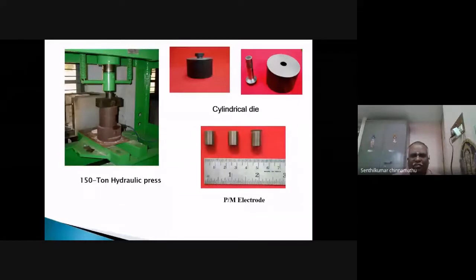And finally, we have to compress the powders inside the cylindrical die with the help of this 150-ton hydraulic press. Various pressures have been selected, and then we study the properties at various pressures to evaluate the coating characteristics. And the powder metallurgical electrodes, that is, the green compact electrodes, were prepared using this 150-ton hydraulic press.